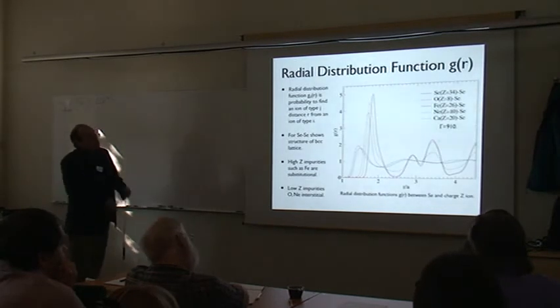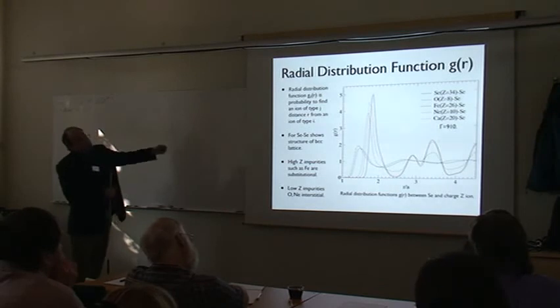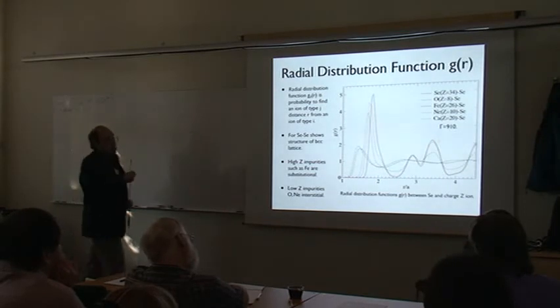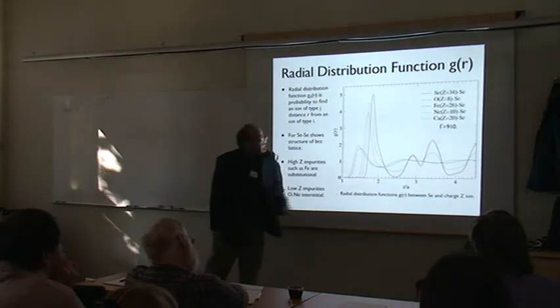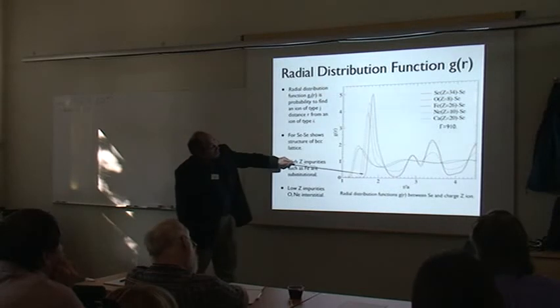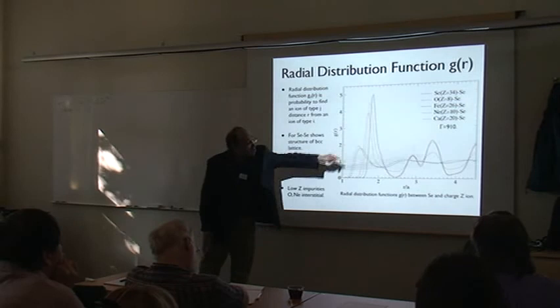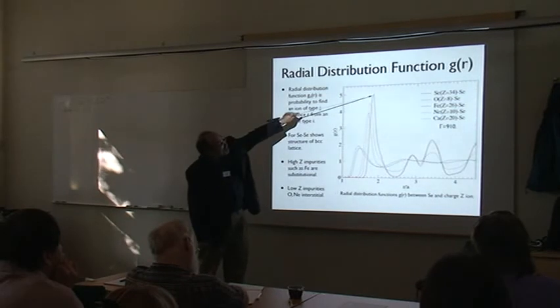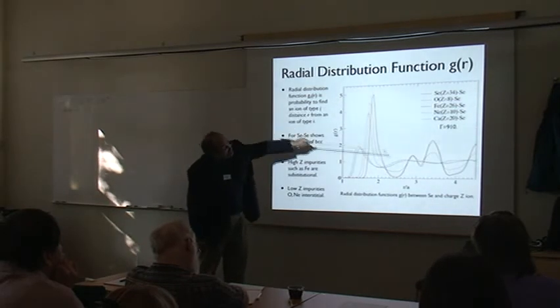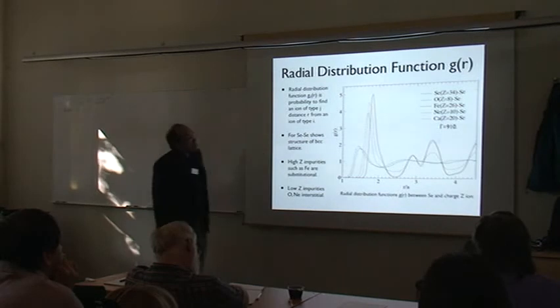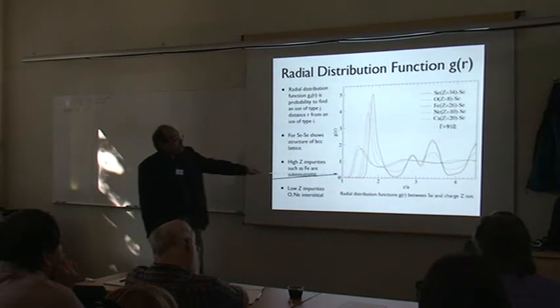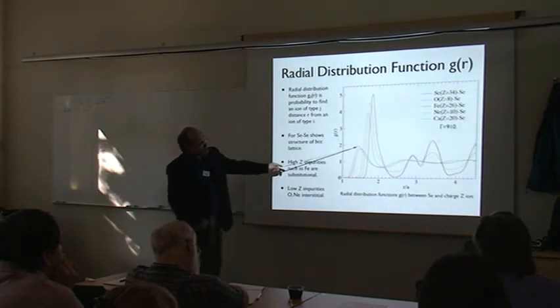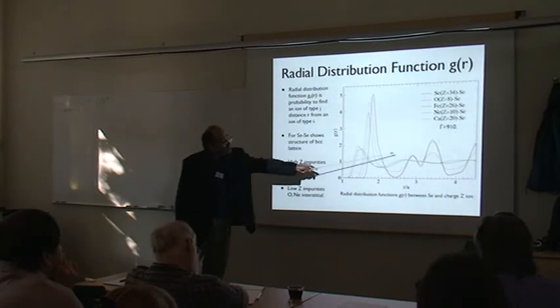You can also look at radial distribution functions. If you sit on one ion, what's the probability of finding another ion a distance r away? If you sit on a selenium ion, the probability of finding another selenium is this black curve. This is the nearest neighbor, this peak over here is the next nearest neighbor, and so on. If you sit on an oxygen, the probability of finding another selenium gives a very different curve.